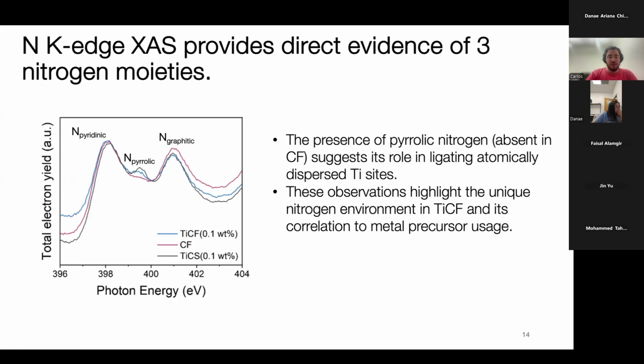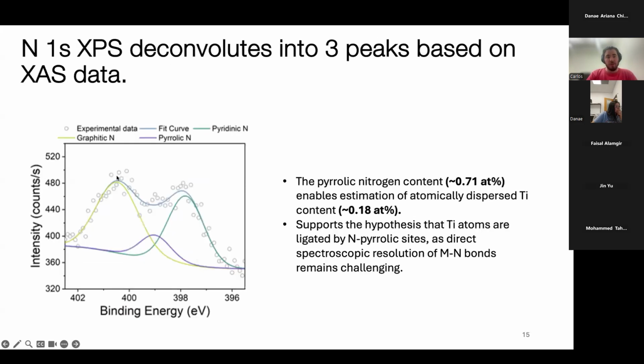And the other thing that we know here is the structure, we're expecting those three peaks. So when we do N1s XPS, we can deconvolute it into three peaks based on the XAS data. So we deconvolute it into the graphitic, the pyridinic and the pyrrolic curves. And then from the XPS, we can estimate the atomic content of this pyrrolic nitrogen, and we estimate it to be around 0.71 atomic percent.